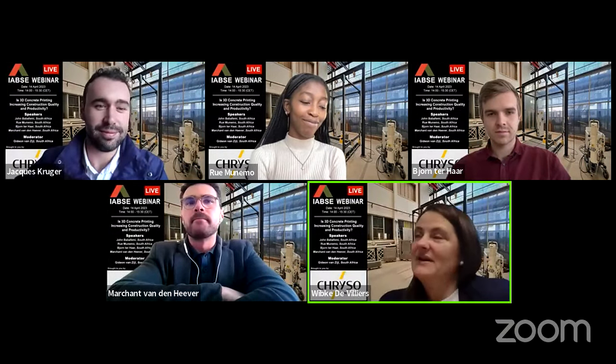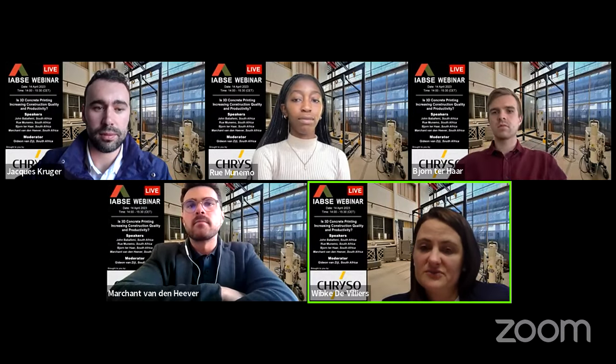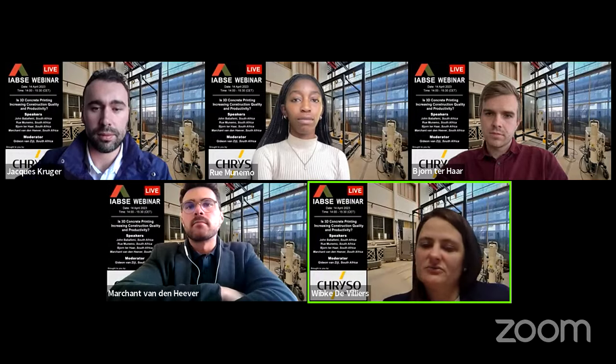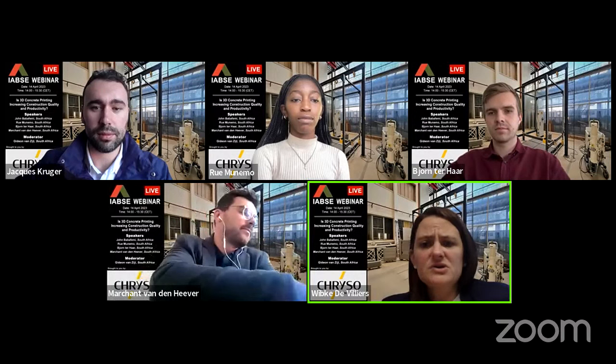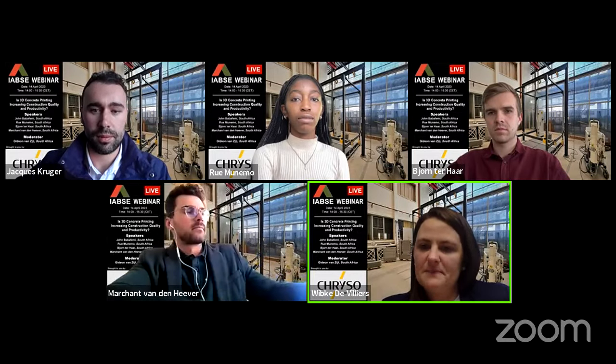Thanks, Jacques. Yeah, so at the end of the day, even though it's printed, it is still concrete. So on the material side, it is basically still a concrete material. But the big advantage of 3D printed concrete that we need to leverage in terms of thermal is the complex geometry that you can print. And so, as also indicated earlier, PhD student Heidi Christen did thermal tests on a 3D printed facade, specifically with phase change materials included in the recycled brick aggregate, which performed really well, but that's specifically on the inclusion with PCM.